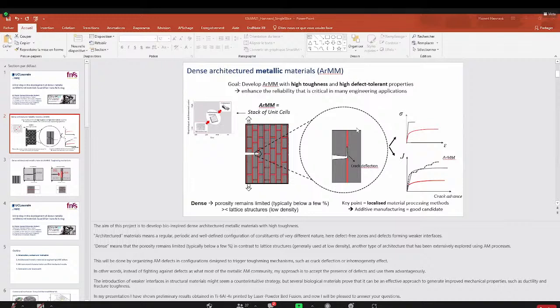But then if you watch the video, you also have seen that I'm working on different strategies. So not only using porosities, but also, for example, using a dilution effect in such a way that we, for example, control the amount of molybdenum that goes into a titanium matrix. And so for this strategy, to be clear, I started with controlling the defects, because it's the easiest one and it's kind of a proof of concept, at least for toughness. But definitely, I'm doing fracture testing at the moment, and if this is giving promising results, then definitely with the other properties, we will also look at fatigue. But I cannot really tell in advance.